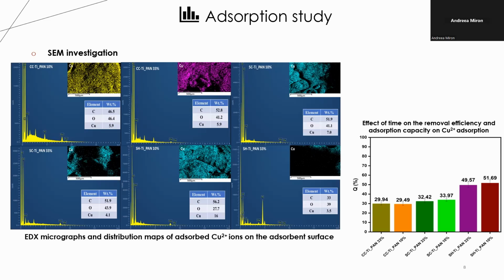Using SEM microscopy, elemental mapping, and EDX spectra, we collected data for all the series of composite beads after the copper ion adsorption. In the figure, we can see the EDX spectra, which confirm the presence of the major constituents of chitosan, carbon and oxygen. In addition, a significant amount of copper was found on the surface of polymeric beads, with percentage ranging between 3.5 to 16% for the best sample.